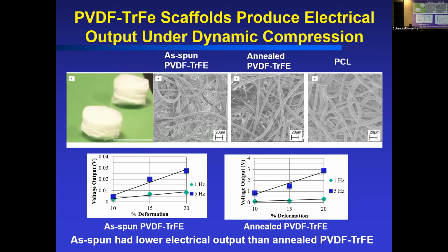So we performed a study looking at the effect of different processing, even post-processing, of these materials, such that we can get a difference in that voltage output. So if you apply a load to these materials, you'll get either a lower or higher charge. And so we have this as-spun formulation, or we have this annealed version. In this annealed version, post-processing, we heat treat it, we are able to get a higher piezoelectric crystal formation that gives us a higher charge. And so shown down here, we are getting voltages or fields on the order of about 10 millivolts per millimeter. And on the higher annealed version, we're getting almost on the order of 100 millivolts per millimeter, depending again on that frequency and deformation that we're applying.